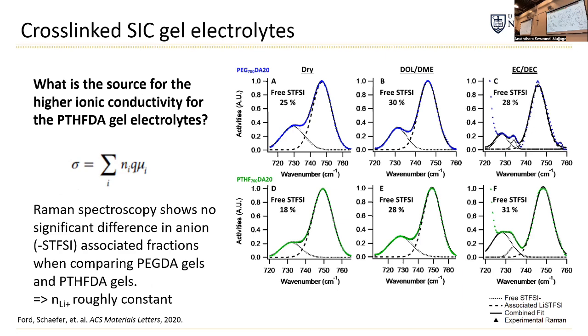So at first we thought that maybe there's a difference in how the cation is interacting with the TFSI that's on the polymer backbone. And so we've been doing a lot of Raman spectroscopy in the group, so he applied that in this case as well. And these are the Raman peaks that you get for the anion itself. So TFSI is kind of a bent structure, and it modulates like this, and there's a Raman band that correlates.